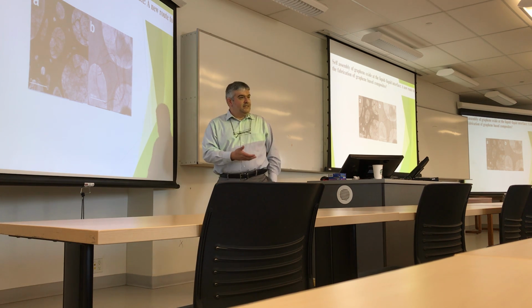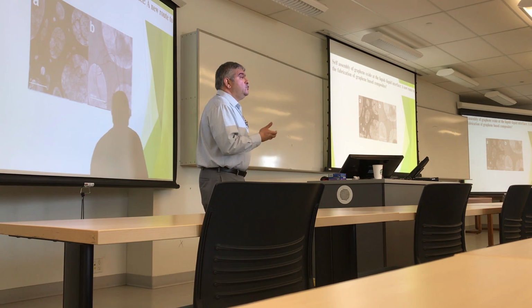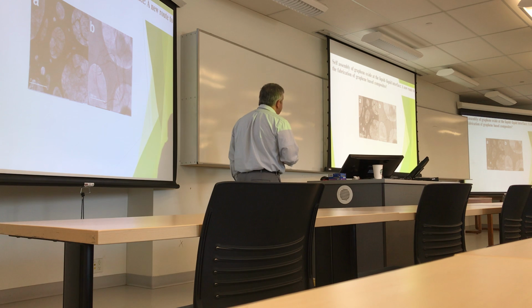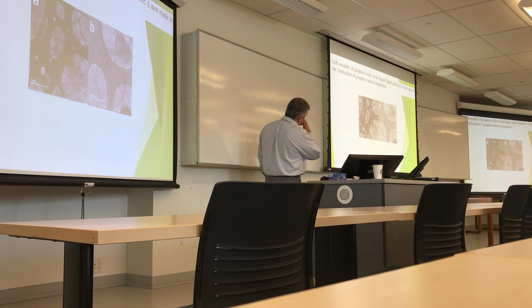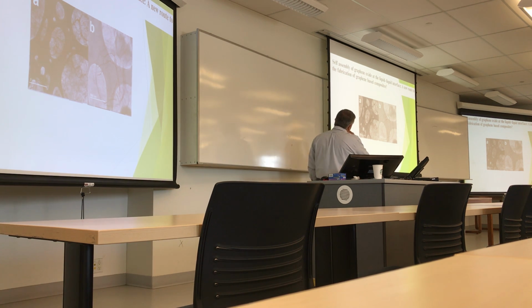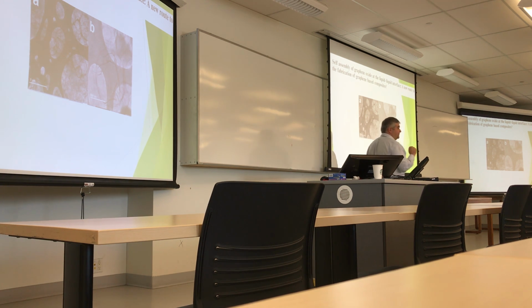So we used it as a surface active agent, and we used the Pickering emulsion. In this picture, what you see is that there is oil and water and GO, and these are the pictures that we have taken from the bubbles that we made. It's really hard to see, but there are small bubbles that are wrapped in GO layers.